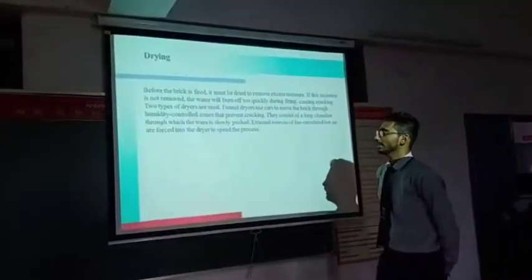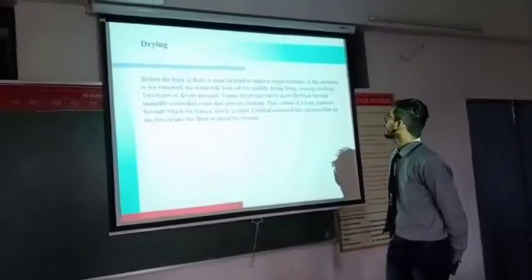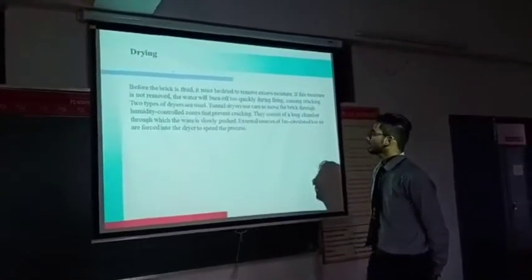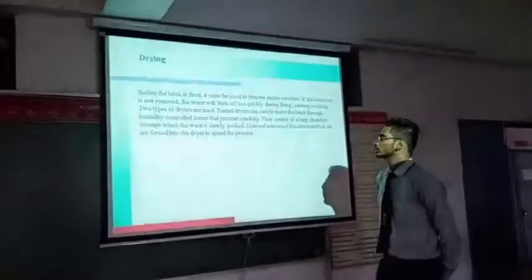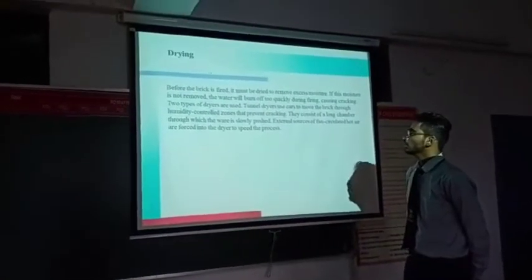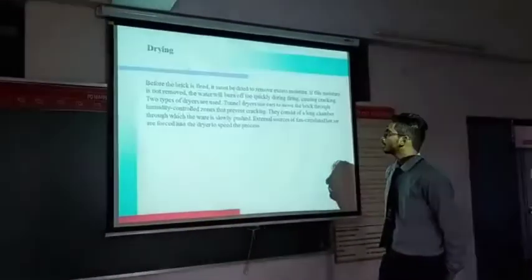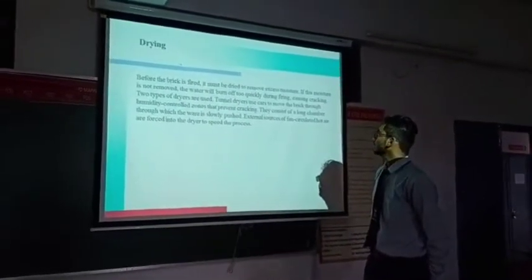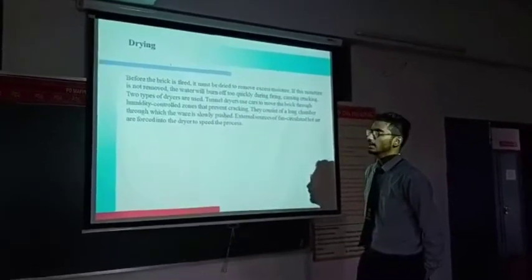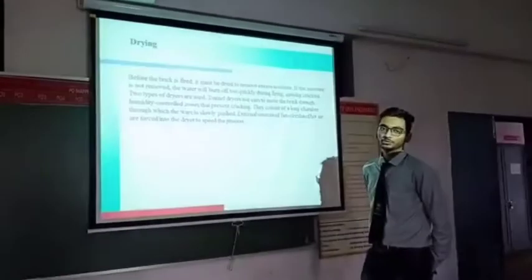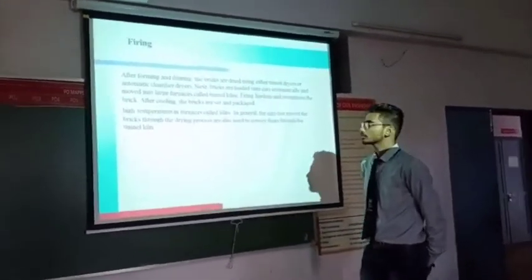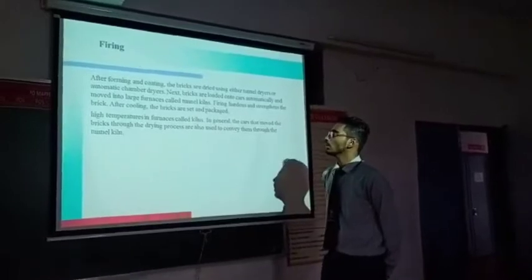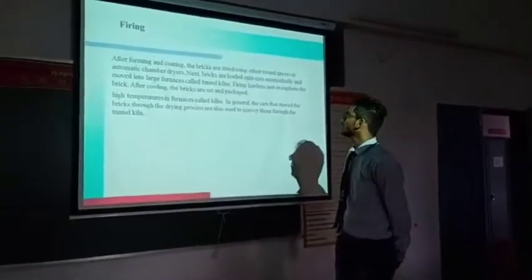Before the brick is fired, it must be dried to remove excess moisture. If moisture is not removed, the water will expand causing cracking. Two types of dryers are used: tunnel dryers which move the bricks through controlled temperature zones to prevent cracking over an extended drying period.